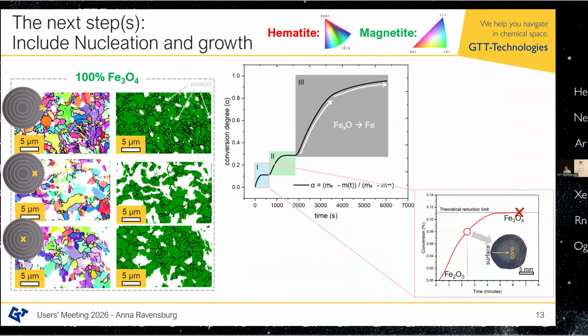So we have taken a pellet out that was reduced from Fe2O3 to Fe3O4. It could only be reduced to this. And we took this point here and stopped the reduction at 100% Fe3O4. And then at different points in the location, so at the bottom is the core of the pellet, the top is the surface, and the middle region is something in between. We looked at how the grains actually grow. And in the green plots, you can already see, okay, there's a difference in porosity. We have more bigger pores at the core of the pellet. We have more smaller grains at the surface of the pellet, which is also the region that first gets reduced because it's first in contact with the gas.